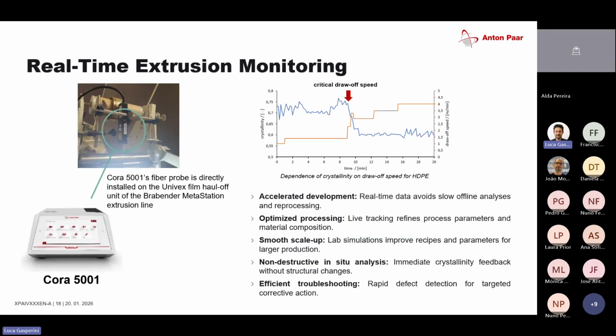Then this is the second thing: we were extruding a film. In this case it was an HDPE film, and we were using the Raman probe at the film draw-off. So we were collecting the films all the way when it was already cooled down. So why is this of interest?